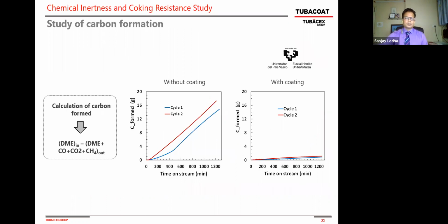So this slide shows the carbon forming reaction, and basically we just do the equation through which we know how much carbon is formed. And again, what you see here is without coating and with coating, there's a huge difference in the amount of carbon that you make, a factor of 10 times lower carbon formation.